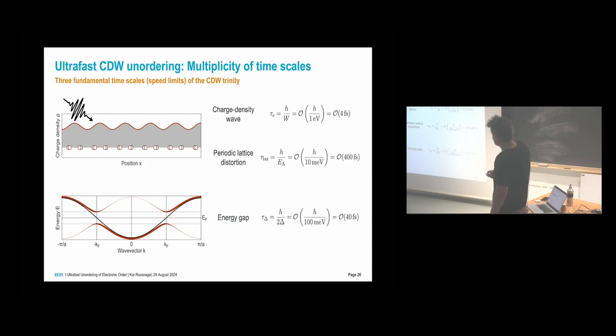So for the charge density modulation, you need to move electrons from here to there, let's say. And what is the time scale of electron motion? It's the hopping time scale, h over your bandwidth, so this gives you a 4 femtoseconds time scale. If you want to undo the periodic lattice distortion, you have to move atoms. And there, the relevant time scale is the energy of a phonon vibration, so 10 millielectronvolt energy scale of phonons, so the oscillation period of a phonon is about 400 femtoseconds.